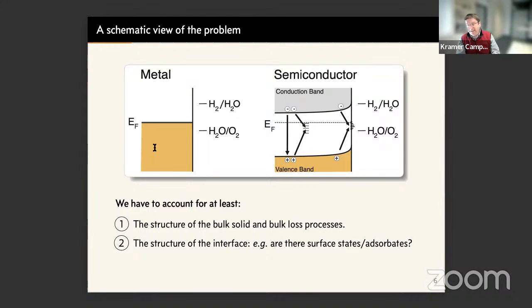Life is a little more complicated, right? If you consider semiconductor materials, here you have a conduction band and a valence band. Of course, you also can define a Fermi energy, but there are no density of states near the Fermi energy for the ideal semiconductor. And so one is left now with a situation in which the effect of changing the bias is to bend these bands and favor the flow of electrons to or away from the interface. But the physical picture is the same, right?